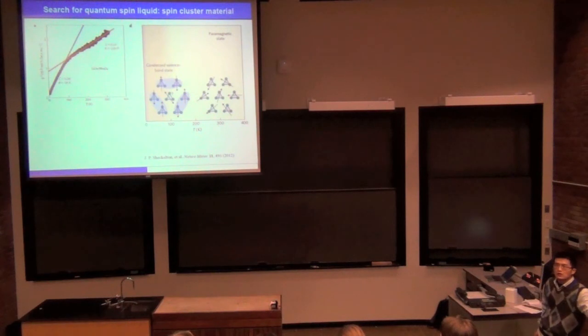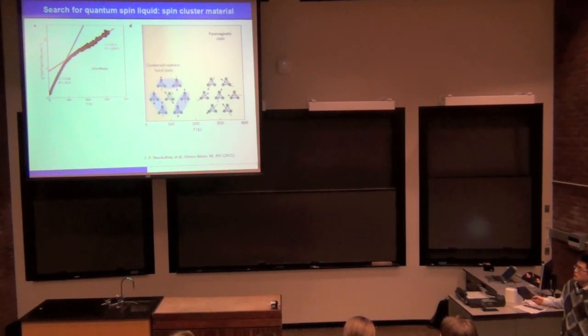Oh, okay. So it's not actually breaking the symmetry. Right, exactly. So they measured the structure carefully. If it were a static configuration, then you would expect a breaking or lowering of the lattice symmetry. And this was not seen in any of the measurements.